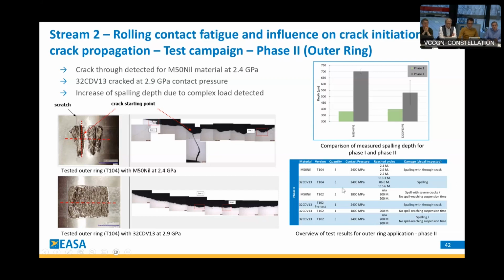In this overview here, you see the tests being performed with M50 nil and with 32 CDV13, and you see a slight variation on the notch. You see also that we had several quantities and we had a pre-test done. You see it here, the pre-test. Sorry for that, go back. For the pre-test, for example, we had a spalling with a through crack. And if we then look at the same test here, we had the spalling, but no cracking through. So we had some problems getting this cracking, which was further analyzed. But at the end, you see that you can initiate the cracking.